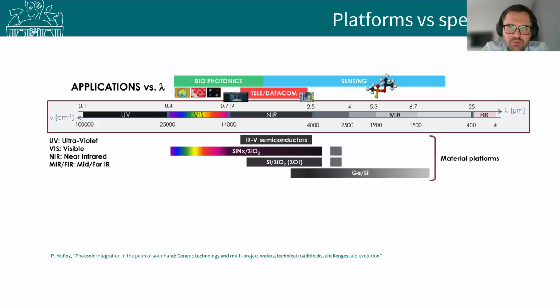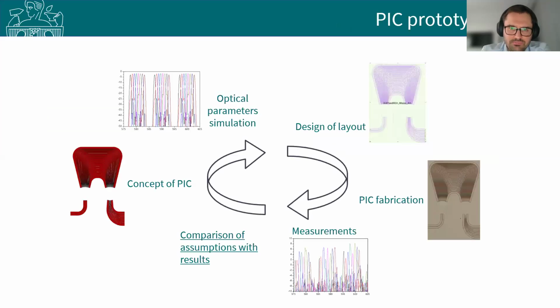So for sensing, the whole spectrum is interesting, starting from visible, which is covered by silicon nitride and polymer platforms, through near infrared, which silicon on oxide, also silicon nitride and III-V materials can cover, and mid infrared, which is covered by germanium on silicon, lithium niobate platform, and also some silicon-based platforms, but without oxide below the waveguide.